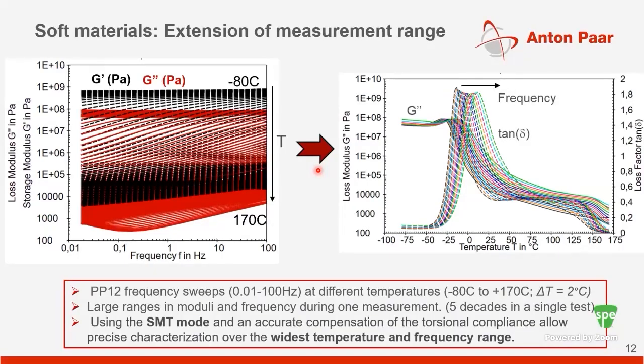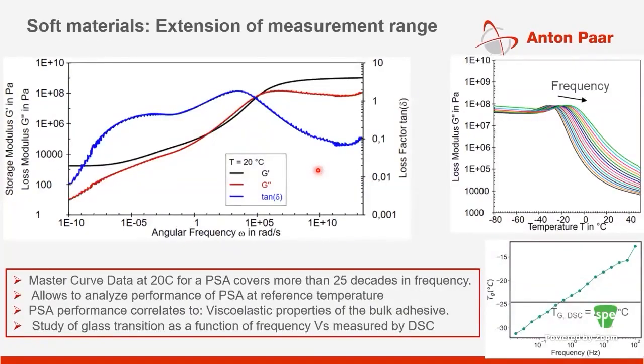This will be clear in the next slide, where typically PSA performance is correlated to viscoelastic properties of the bulk adhesive. The data I showed you earlier can then be used with time temperature superposition to extend and generate master curve data, as shown here, spanning almost 25 decades in frequency.